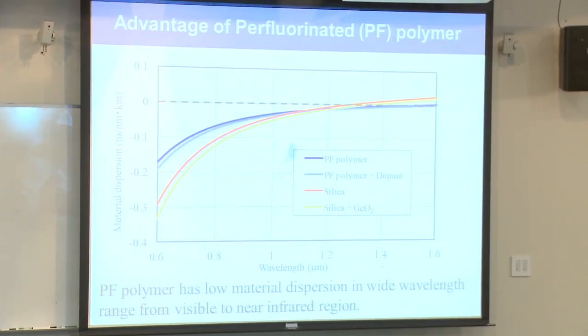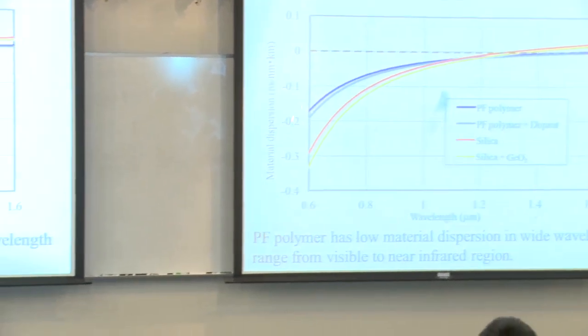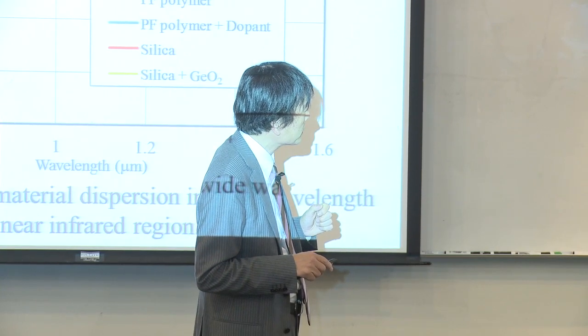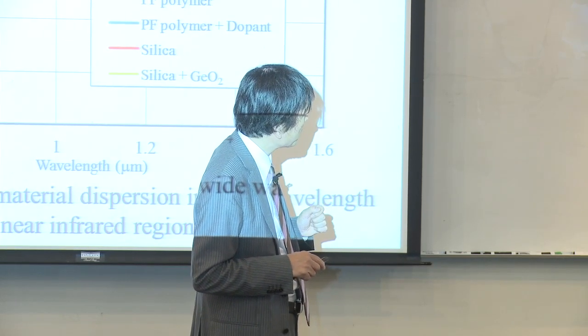And also, the second advantage of this perfluorinated polymer is that the material dispersion is smaller than even silica material dispersion. The reason why silica has the 1.3 micron is that at 1.3 microns, the material dispersion of the silica becomes zero, and crossing the zero line it becomes plus. But the important wavelengths for plastic optical fibers are here. This value is smaller than silica.